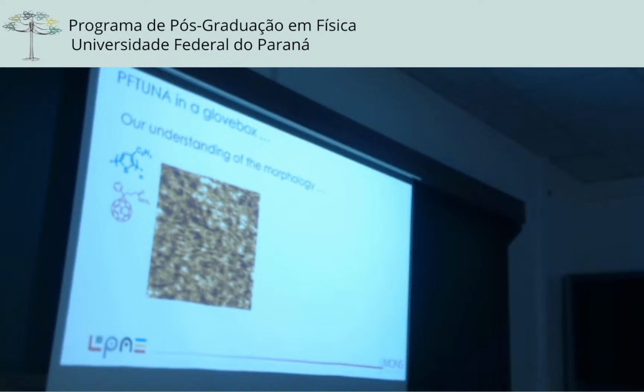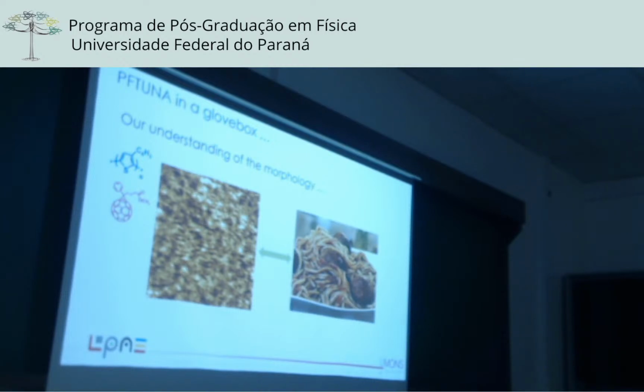So you can see the fibers, you can see the domains, and we have this situation. Our understanding of the morphology, with the P3HT fibers surrounding the PCBM aggregate, is something like that. So this is what we think we have in our system. The PCBM domains are surrounded by the P3HT fibers.